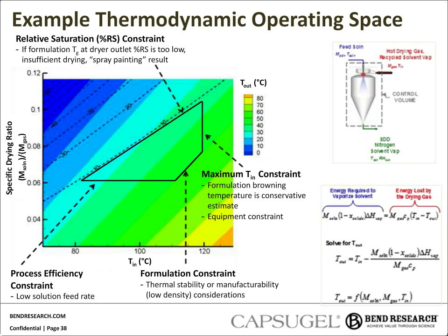As you go up on this axis, spray solution feed rate or dryer throughput goes up. Within the graph are contours of constant dryer outlet temperature and isolines of constant relative saturation at the dryer outlet. The lower right-hand corner is the hotter, drier space, and the upper left-hand corner is the colder, wetter space. This type of graph can be used to lay out your operating space and identify your key thermodynamic parameters. For instance, a maximum inlet temperature can be determined based on either properties of the material, say its browning temperature, which you may want to stay below to ensure that any deposits near the lid, which can have local hot spots, don't degrade or brown, or there may be just equipment constraints with, say, the process heaters limiting your maximum inlet temperature.